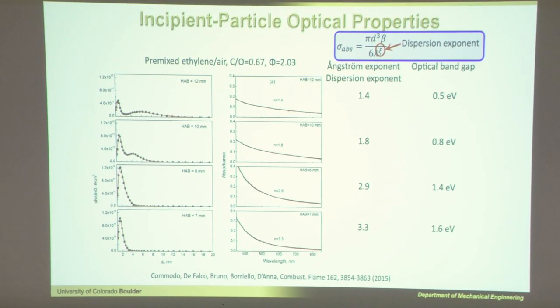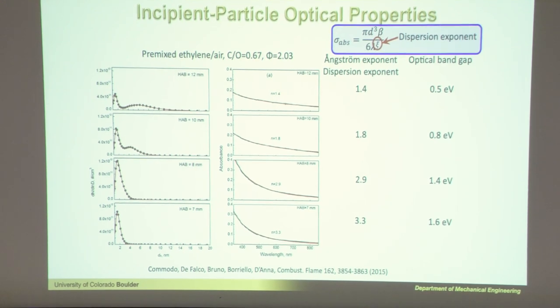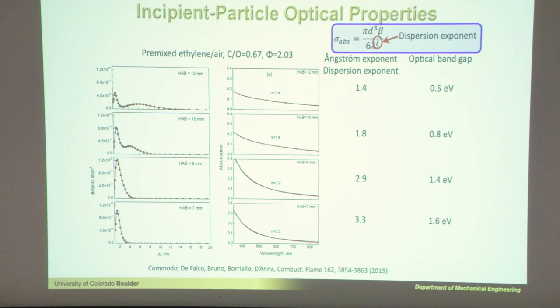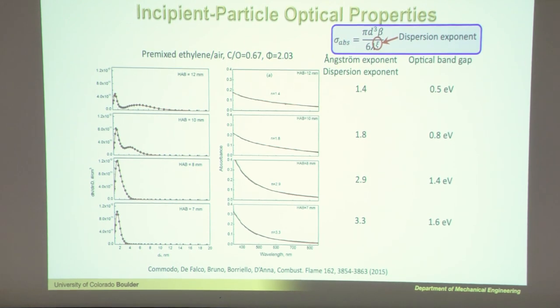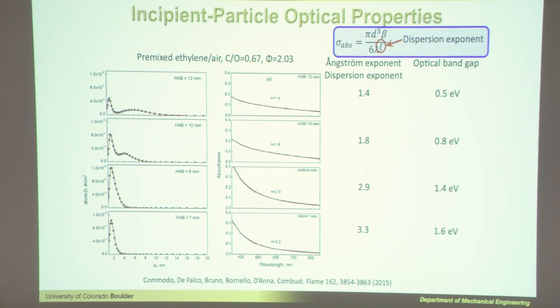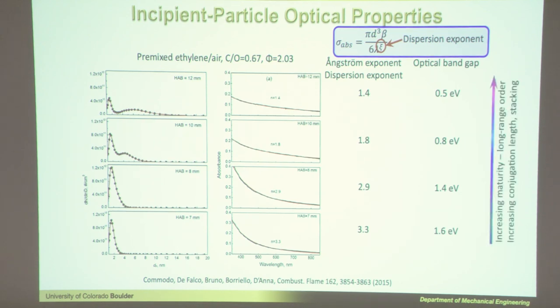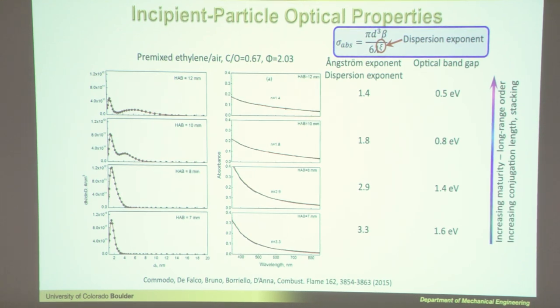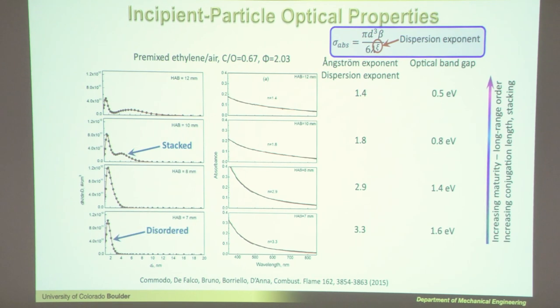People also often talk about the optical band gap. This is another measurement usually derived from these spectra, and it tells you basically what kind of absorption you can get from a particular material. The optical band gap also gets larger as the dispersion exponent gets larger. From the optical band gap, people back out how big the sheets of graphene are that are stacked on top of each other. Increasing maturity increases what we call the long-range order — also called the conjugation length — and it also increases the stacking.